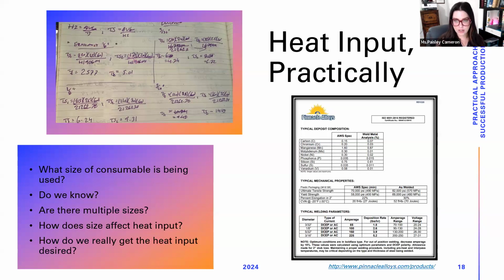To get your heat input to what you actually want it to be, your best approach is to give the welders the travel speed and their amperage. Their voltage, there's not as much control on it in more manual processes like TIG and stick predominantly. So if you give a welder, hey, this is going to be your amperage range, and this is how fast you need to be traveling with your wire, you will be a lot more successful in getting the actual heat input that you want, or the range of it.